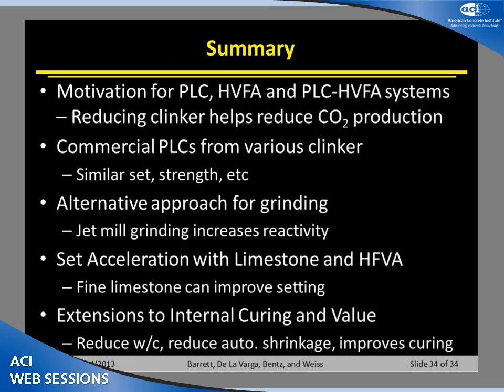So in summary, some of the motivation, really the idea is to reduce the clinker. It helps to reduce the CO2 production. We've shown commercial PLCs from a variety of clinkers, similar set, similar strength, and really the whole idea here is they're at a point where they're really able to be a direct substitution for an ordinary Portland cement. An alternative approach for grinding, jet mill grinding, is a technology that we're really looking at. By grinding, it increases the reactivity so we can really accelerate the hydration of these materials and maybe reclaim materials that are already sitting on the ground.